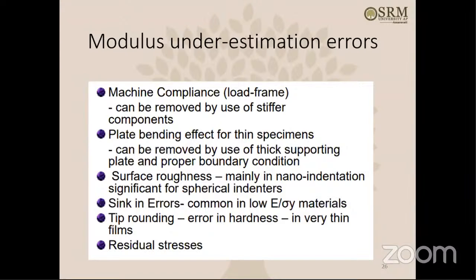But if you can come up with some statistical correction equation, then you can use that and correct for this load frame compliance. Plate bending effect for thin specimen. If the specimen is very thin and it is supported on two edges, then sometimes the specimen may bend slightly. And the specimen is not supposed to bend while doing indentation. Okay, the specimen should be rigid, and the indentation should happen very smoothly. The specimen should not bend. So this bending effect also causes some underestimation of the modulus.